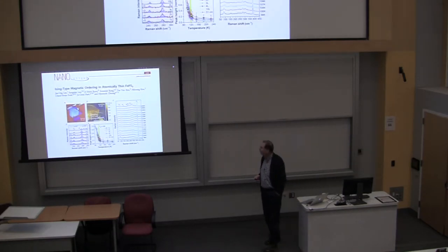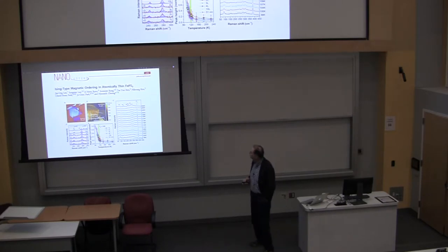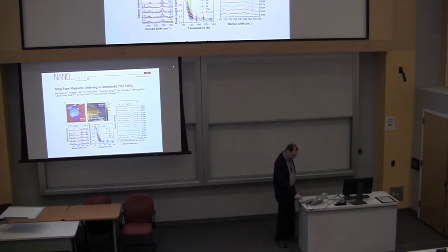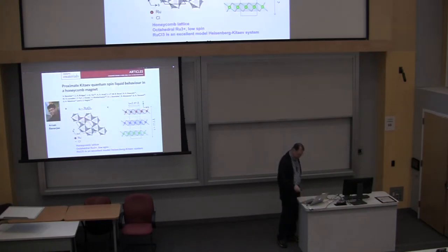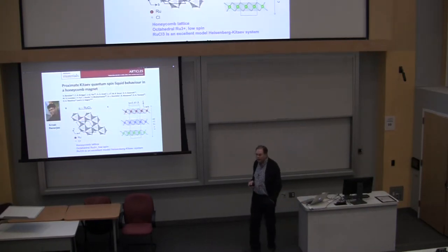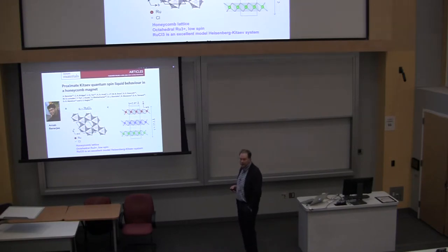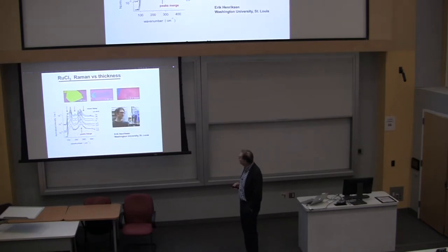People are also looking at antiferromagnets. Here's an antiferromagnetic material, iron phosphorus sulfur 3. So one thing we've been looking at is ruthenium trichloride, which is very close to a Kitaev spin liquid. And actually, if you put a magnetic field in the plane, it does produce some sort of a spin liquid. We're not sure if it's Kitaev or not, but it is a spin liquid. And we've been working with a guy named Erik Henriksen at Washington University in St. Louis, who's an assistant professor there. He's been doing some good stuff.